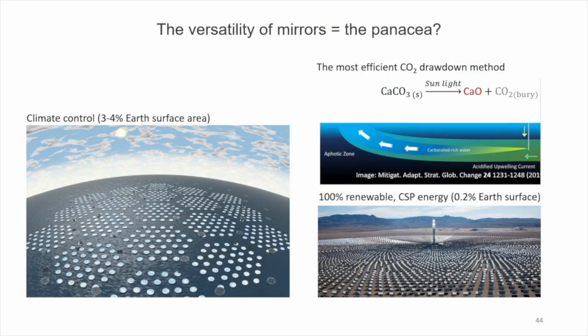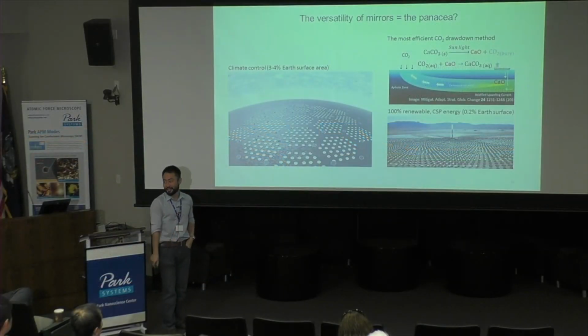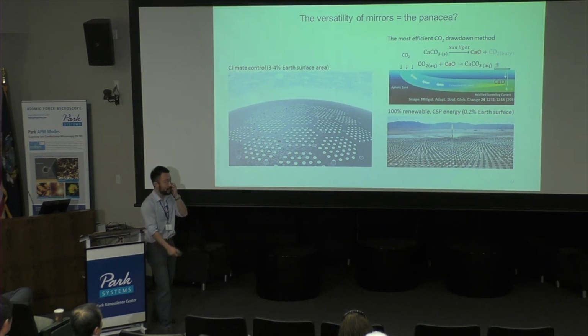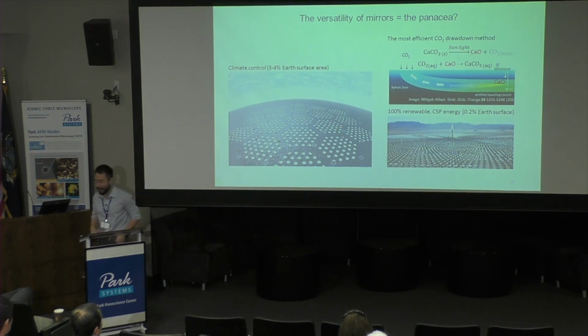And we take that calcium oxide that's resulting from this conversion process. We ship it to the sea, sprinkle it into the sea, and it will react with CO2 that's absorbed by the ocean: large surface area, very fast kinetics, free exchange. And the reaction will produce dissolved calcium carbonate. And that will help the shellfish grow and also neutralize acidity. So that's the most efficient way to do carbon dioxide drawdown.